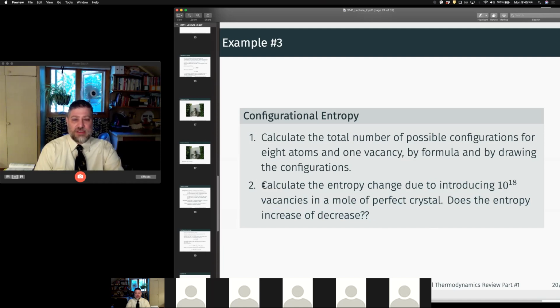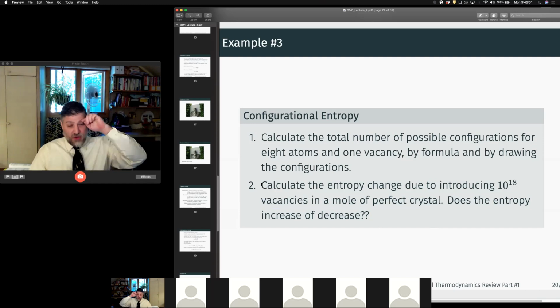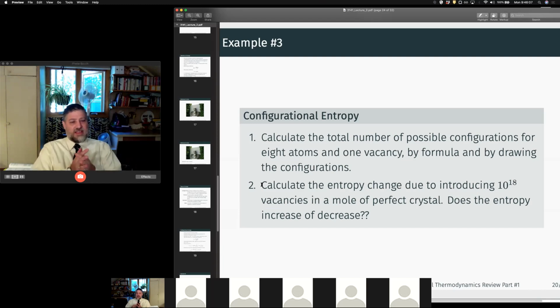phase transformations in alloys such as aluminum, where you have precipitation and growth of secondary phases. At high temperatures, we have a lot of vacancies in our crystal. If I quench quickly enough, I lock in those vacancies. There's not time for them to be removed, right? So I'll end up getting a faster phase transformation in that state in a rapidly quenched material than if I were to cool it slowly.